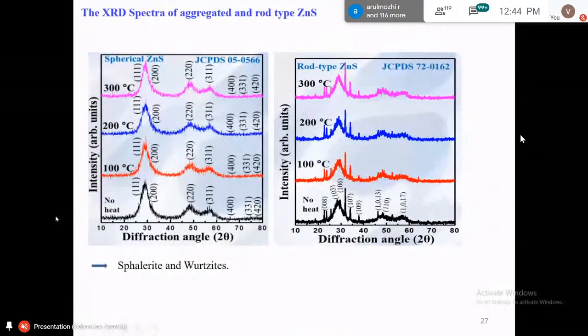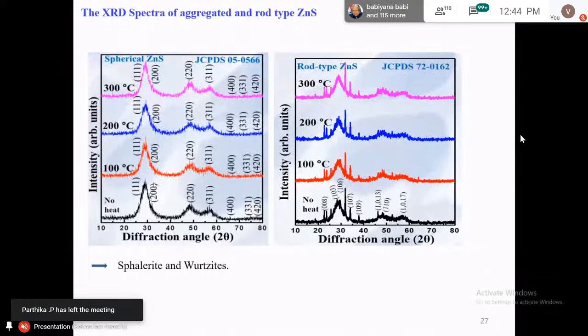And then we checked the XRD spectra of the aggregated and the one-dimensional zinc sulfide. What happens? The spherical, aggregated structure shows sphalerite zinc sulfide. There are two kinds of zinc sulfide found. One is the spherical structure, which showed sphalerite, and the one-dimensional structure was the hexagonal wurtzite zinc sulfide.